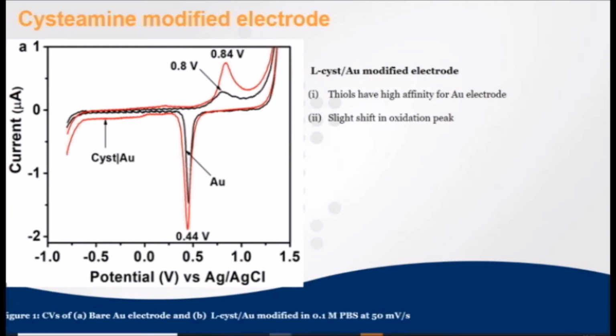The first layer we have is the L-cysteine. What are the signatures of the L-cysteine compared to that of the bare electrode? Because we need to understand our biosensor before applying it. Here the bare is where we were using the gold electrode. Comparing the cysteamine onto the bare electrode, we can see that, of course, we have formed the layer, as thiols have high affinity. Although the signatures did not change that much, we could see some enhancement in the signatures for the L-cysteine. So it means that once you have something on the electrode, you actually have some electron transfer.